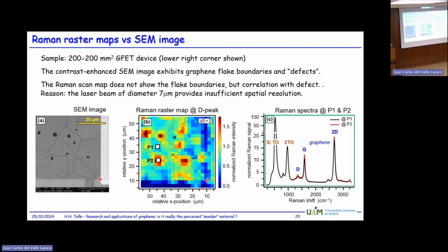If we now compare this with the Raman image, evidently you can associate some of the features with the black spots, so they are at exactly the same position. You can also see, in the picture overlaid here, that the black lines you see in the SEM image are not revealed in the Raman image, simply because, as you can see from the squares, that is the spatial resolution. The resolution here is not large enough to distinguish them.